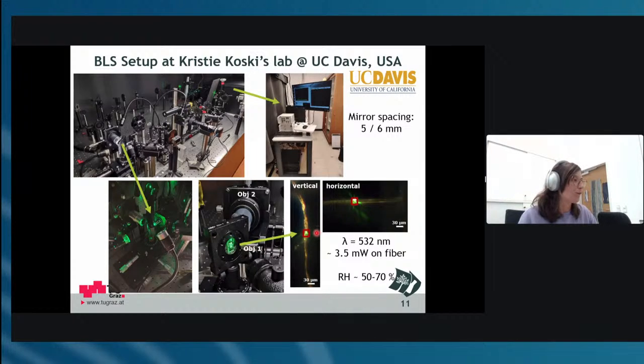Compared to any other of the mechanical techniques, there was nearly no sample preparation, which is absolutely lovely if you have ever worked with single fibers, especially wood fibers. I mean, it's just painful. So I just glued the fibers in and then turned them around in this holder. And what I've tried is to keep the laser power below 5 milliwatts, because otherwise you would burn the fiber and that will also not have a good effect on your results. And what we could not control most of the time is the humidity in the room. So there is no humidity chamber.